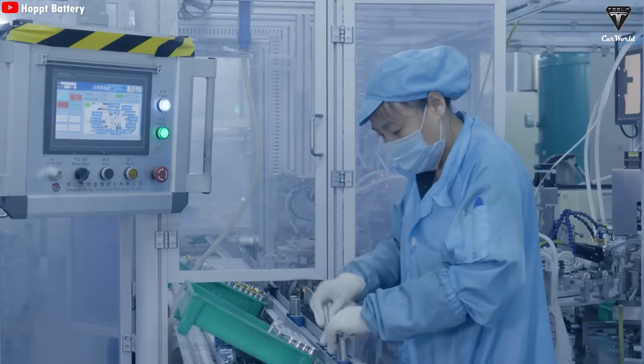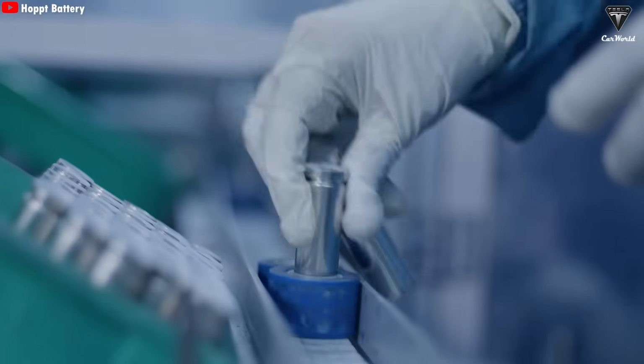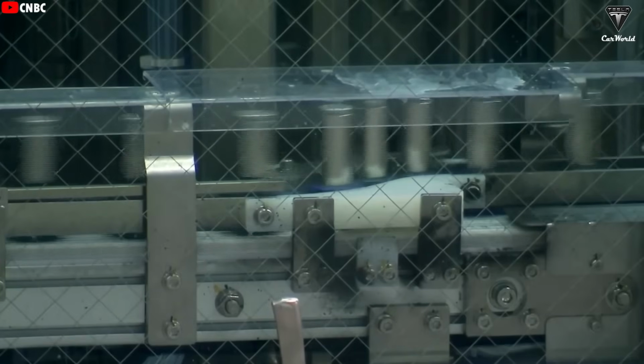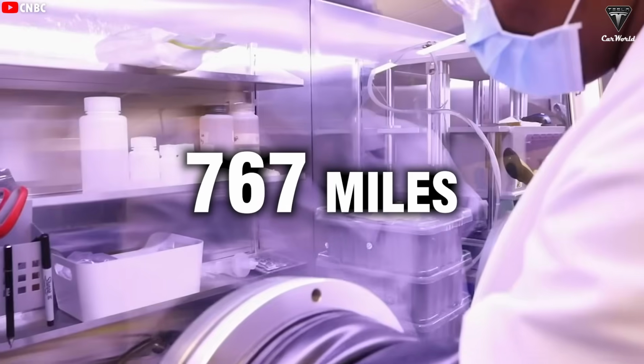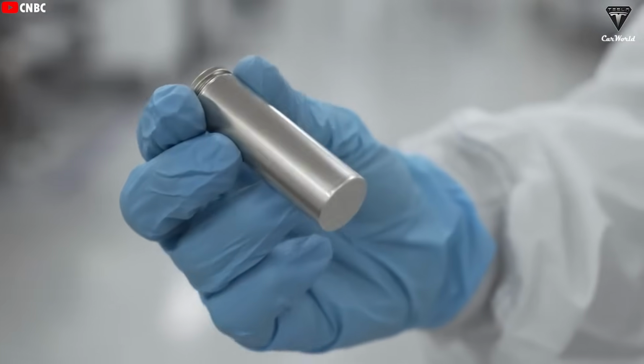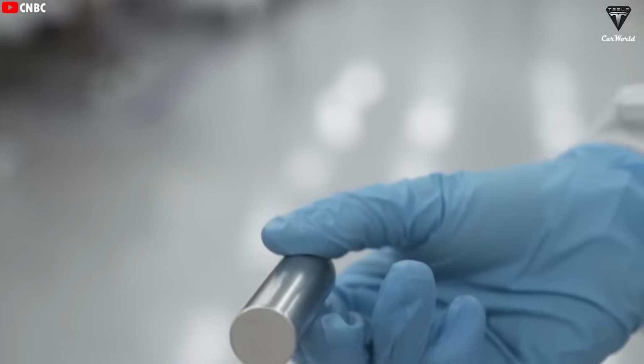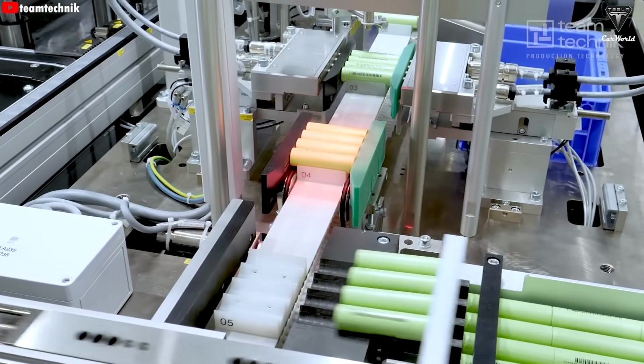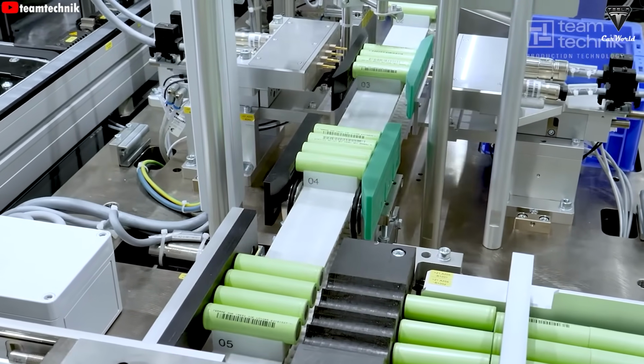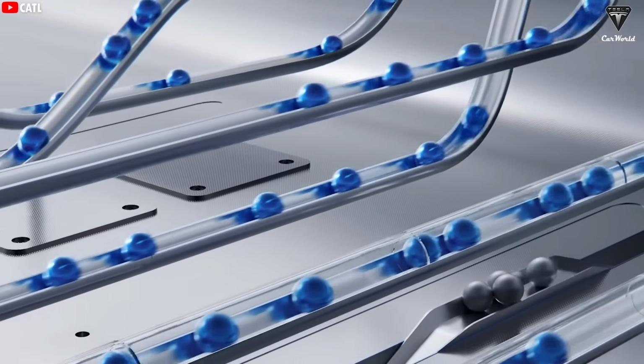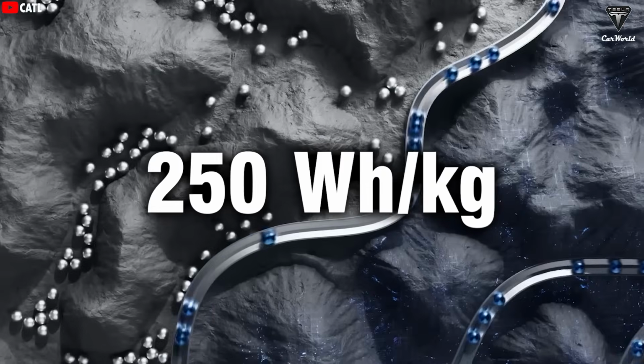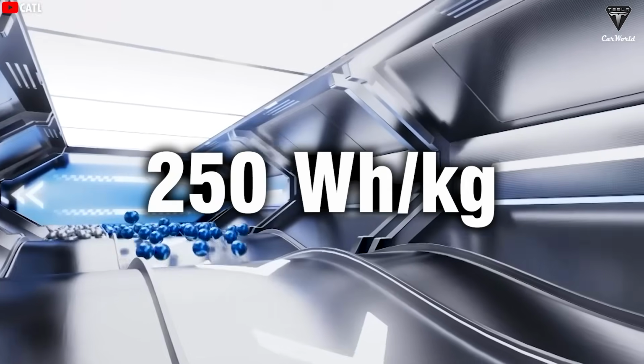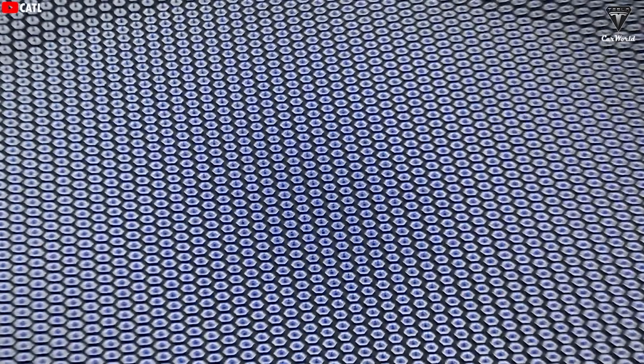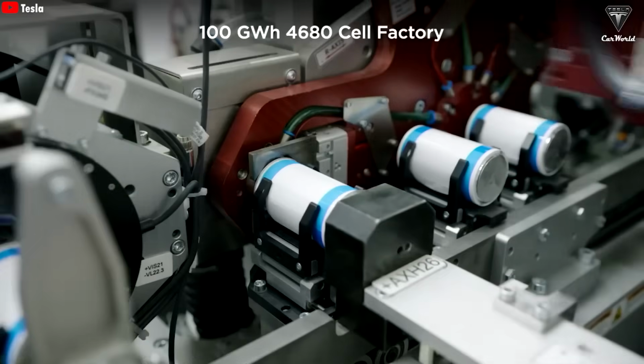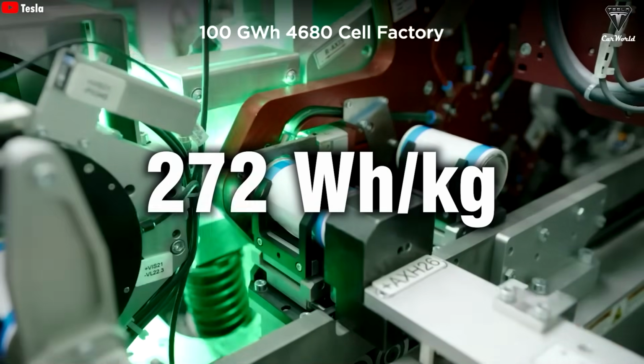With a battery this energy dense, shrinking the pack size is key to cutting costs significantly. So instead of over 1,000 miles, a range of 767 miles is much more realistic. Despite being widely used, as we mentioned at the start of the video, lithium-ion batteries haven't seen any major breakthroughs in recent years, especially when it comes to energy density. Lithium-ion batteries have been stuck at an energy density of about 250 watt-hours per kilogram for decades, and even with Tesla's most aggressive improvements to the 4680 battery, they've only reached 272 watt-hours per kilogram.